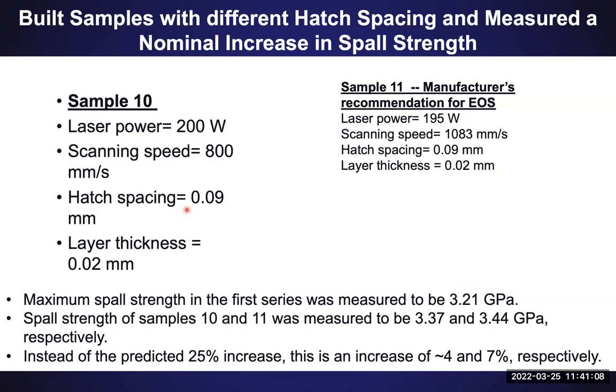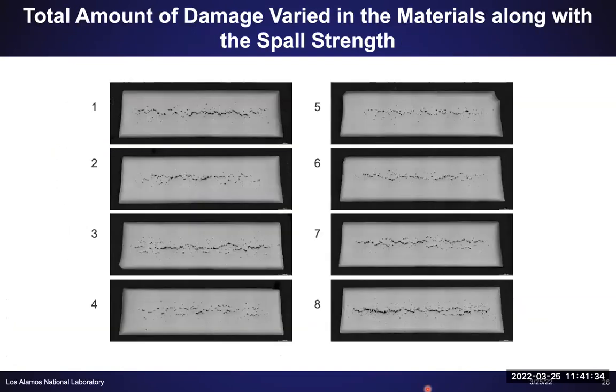The maximum Spall strength that we measured in the old series of experiments was about 3.21 GPa. When we repeated the same experiment under the same loading conditions on these new samples, the Spall strength did indeed go up. But instead of a 25% increase in Spall strength, we got about a 4 to 7% increase. So not a ton, but this was at least able to demonstrate that if we control the microstructure, we should be able to design materials to have very tailored responses under dynamic loading.